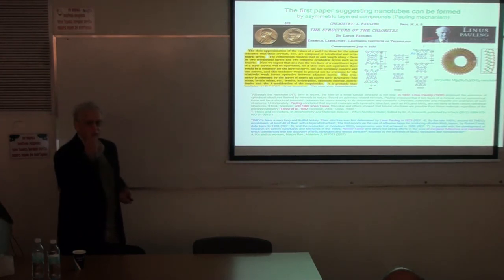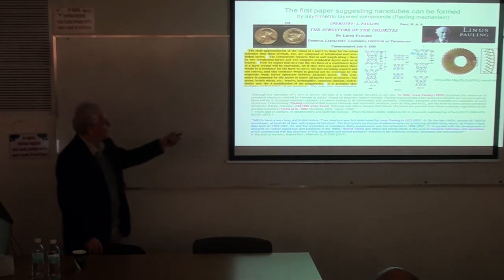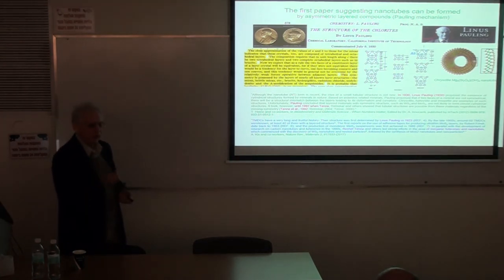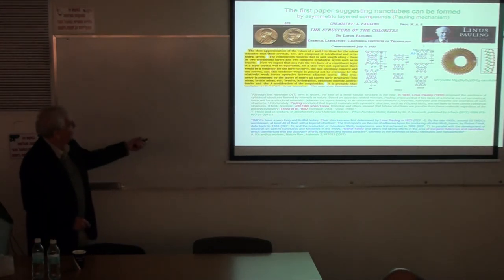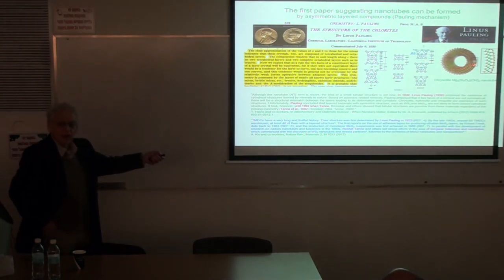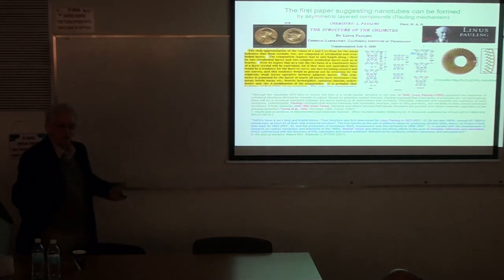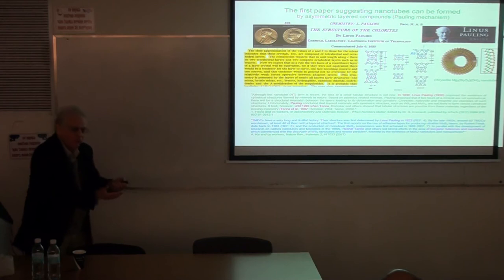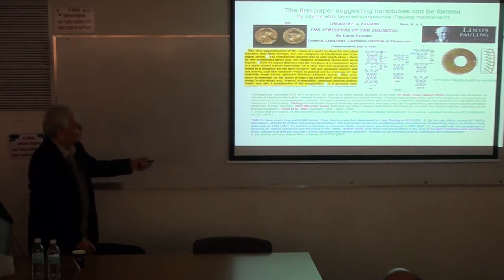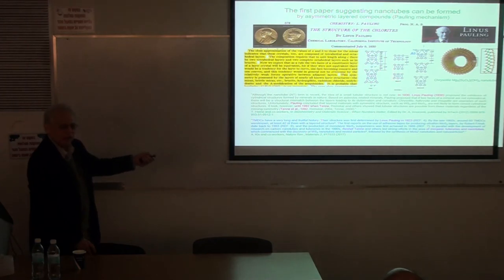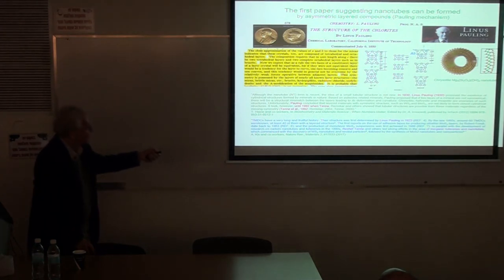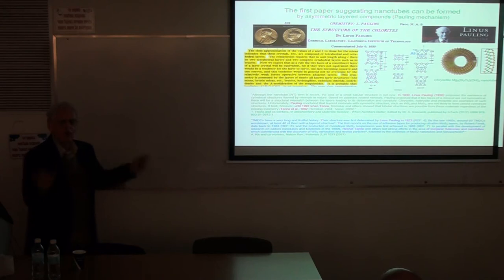In 1930, there were no electron microscopes at that time, and he could describe already the formation of nanotubes from chrysotile. And in the same paper, he stated that chrysotile will form nanotubes because it's an asymmetric compound. The bases here and here, this is the silica tetrahedra and this is the alumina octahedra, are different, and so they are strained and they must fold and form tubes. But a structure like this, which is symmetric along the c-axis, will not form nanotubes. And he mentioned molybdenum disulfide and cadmium chloride and brucite will not form nanotubes.